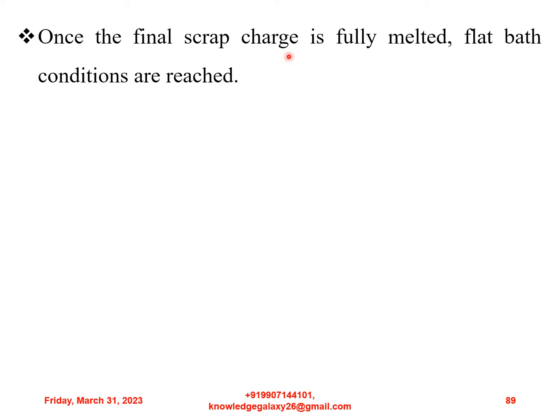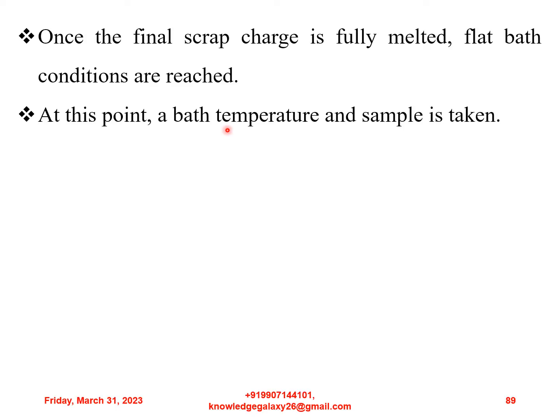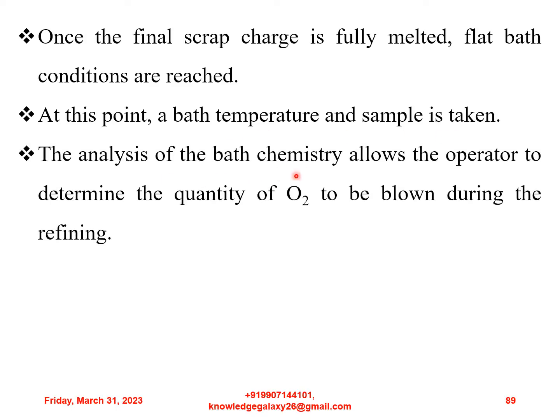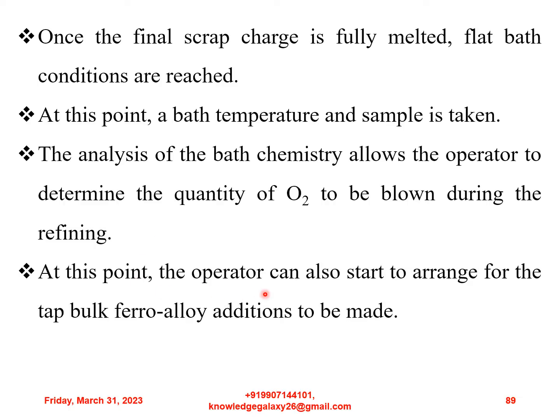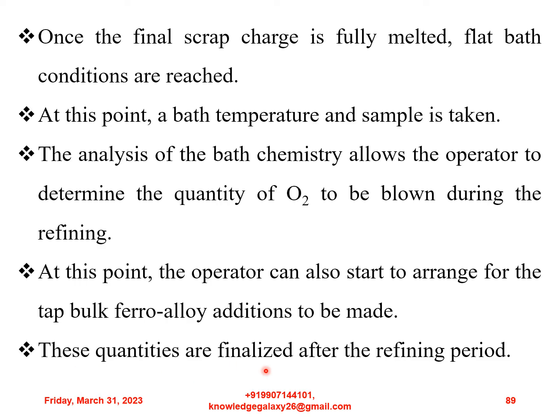Once the final scrap charge is fully melted, flat bath conditions are reached. At this point, a bath temperature and sample is taken. The analysis of the bath chemistry allows the operator to determine the quantity of oxygen to be blown during the refining. At this point, the operator can also start to arrange for the tap bulk ferroalloy additions to be made. These quantities are finalized after the refining period.